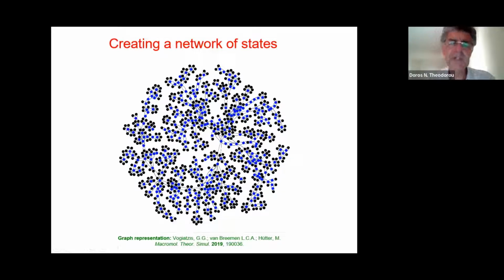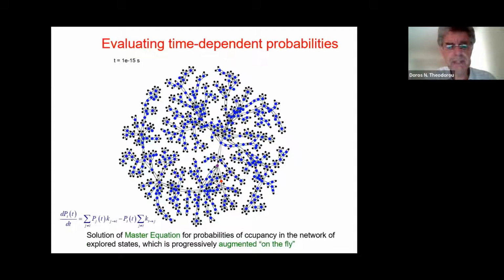So one can use this picture in order to try to examine how the system would relax with time. One can initially place the system within a given minimum, for example, within this red dot, that is one minimum in configuration space. The probability of occupancy of the minima in the network is described by a set of master equations, such as this one, which essentially say that the probability of occupancy of a minimum changes with time because of efflux from that minimum into other minima, and that's what is represented by the second term here, and because of influx of probability from neighboring minima.